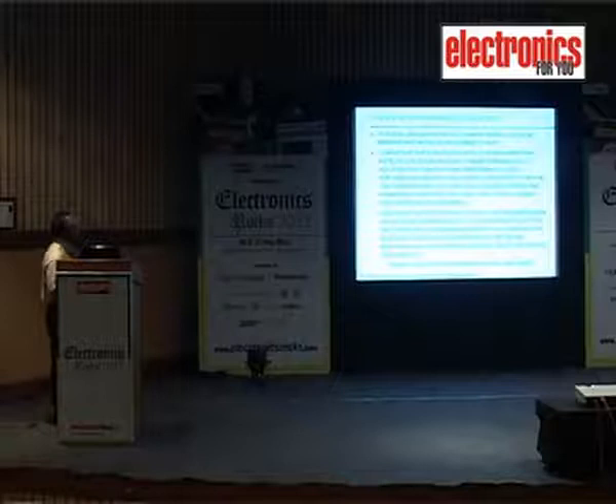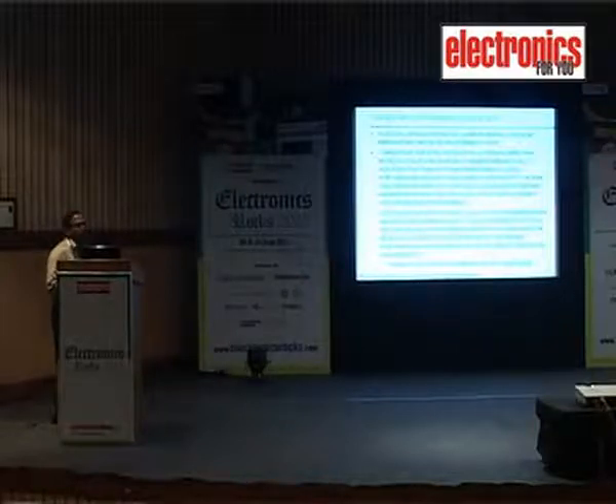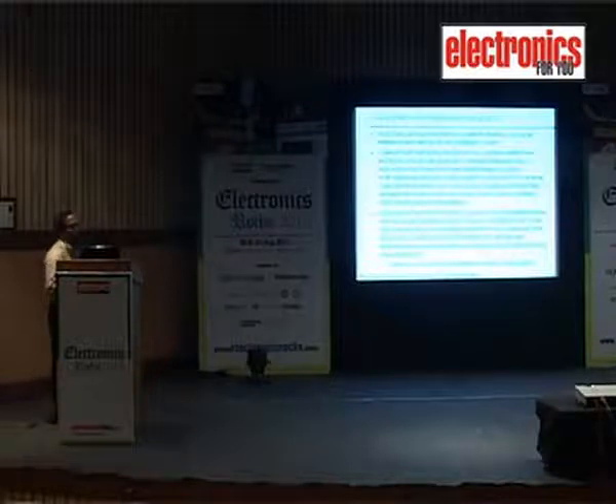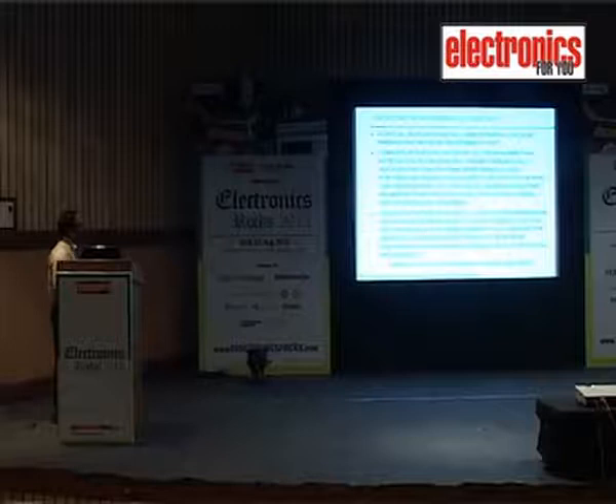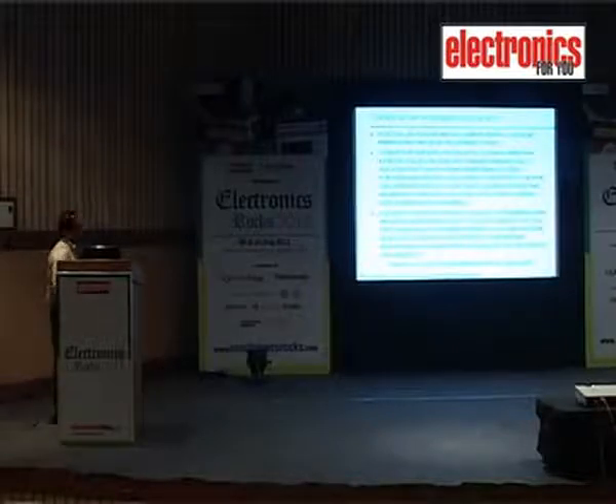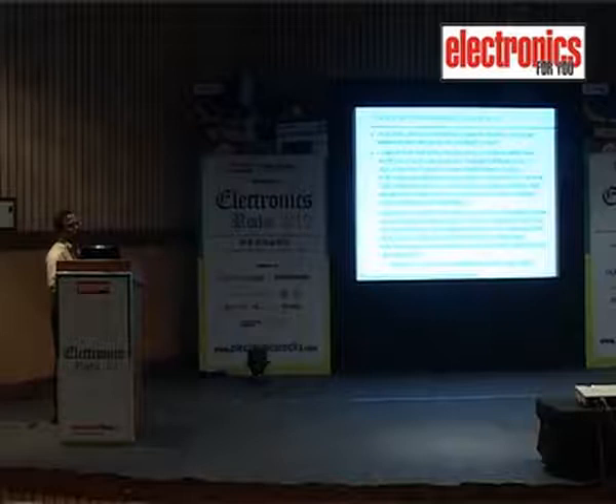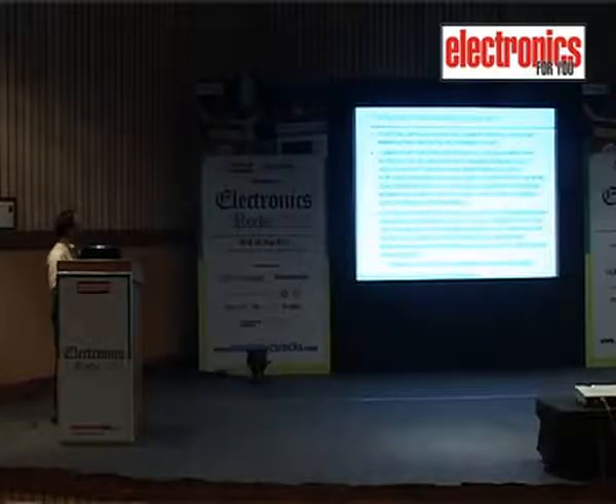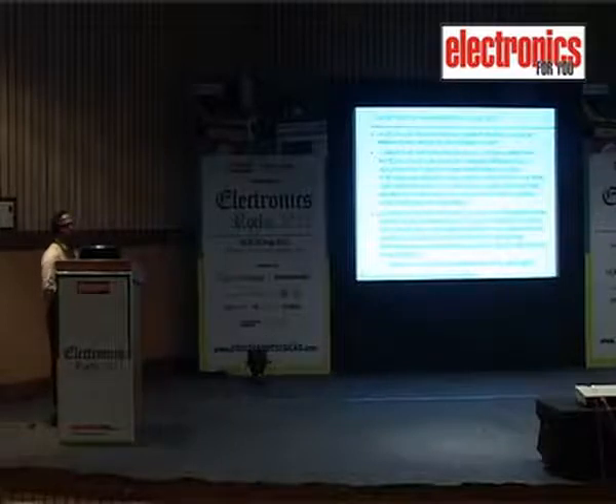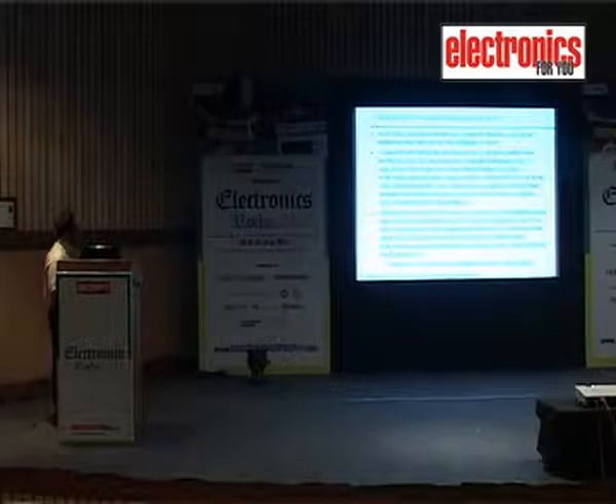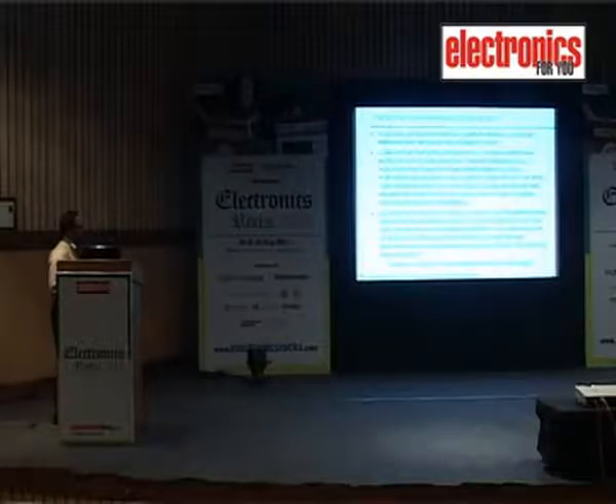Then we have to see dielectric withstanding voltage, because various subsystems, as you have already seen, are used for building up the spacecraft. We have a power subsystem, control subsystems, and sensor subsystems. In the power systems we have a lot of switching relays which can cause surges, and we have power modules which will encounter higher voltages. All these things have to be verified, whether the spacing between the traces and the dielectric thickness provided for building up the multi-layer board is sufficient or not. All of that is verified by the dielectric withstanding voltage test, where we apply 1000 plus or minus 25 volts DC for a period of 30 seconds, and we observe for any degradation in the dielectric material.